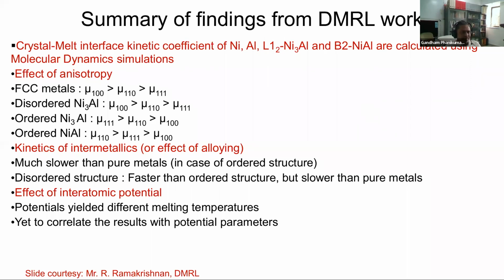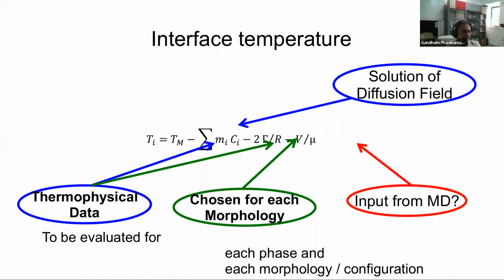So those can be documented from molecular dynamics runs, and they will be directly affecting the morphology formation. Okay, so all those are inputs from molecular dynamics into the mu. The diffusion field can be solved, and that will go to the C. The thermophysical data is available that will give you the surface energy, and the velocity of the laser torch can also be giving you the V here.